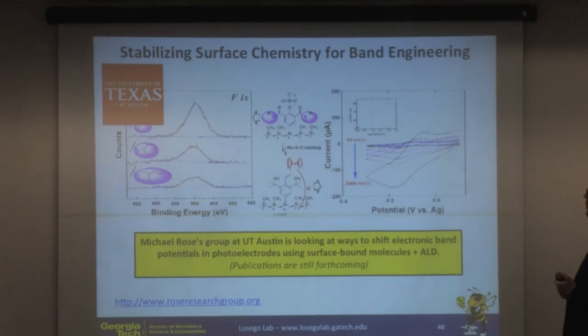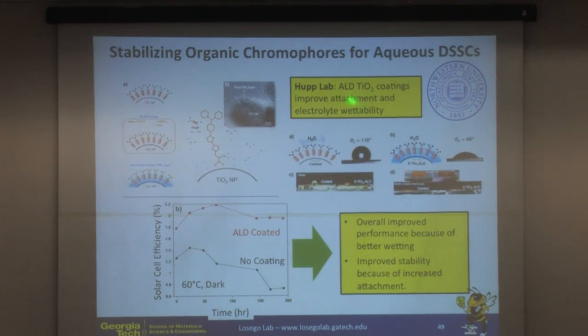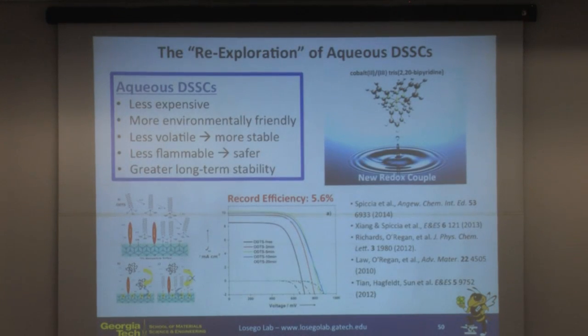So let me show our work in perspective. Michael Rose's group at UT Austin has now begun looking at using ALD to attach molecules to surfaces to shift the electronic band structure of interfaces. There's also very nice work from the Hupp group at Northwestern, where they're using these ALD attached dye molecules for aqueous dye-sensitized solar cells. Not only are they getting increased stability, but they're also improving the wettability of the nanostructure to allow the aqueous electrolyte to permeate the entire structure. I think there's a lot of opportunity in aqueous dye-sensitized solar cells, not only because of our stability demonstrations, but also because there's been work coming out about new redox couples that work more efficiently in aqueous environments.